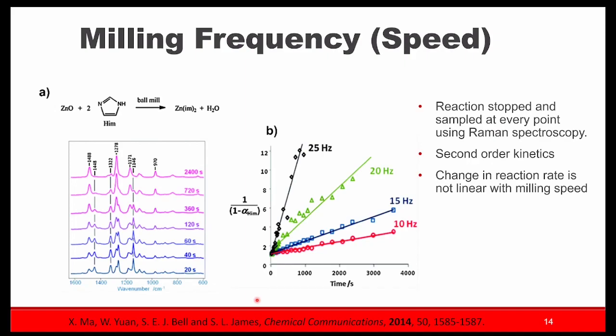This is not research that I did, but this is some great work by the Stuart James group up in Belfast. And so what they did here is they took zinc oxide, which is, again, a nice insoluble metal oxide. They're reacting it with the imidazole, and they're basically tracking the rate of disappearance of this protonated imidazole using Raman spectroscopy. And they're milling at different frequencies. So in this case, that vibratory mill that I was showing you before, the shaker mill, which is going side to side, is oscillating at a frequency of 10 hertz. And then in the fastest speed, it's 25 hertz.